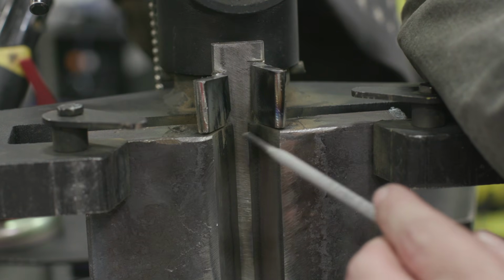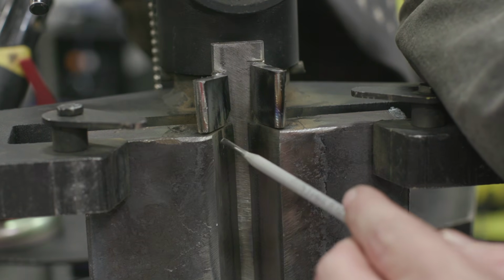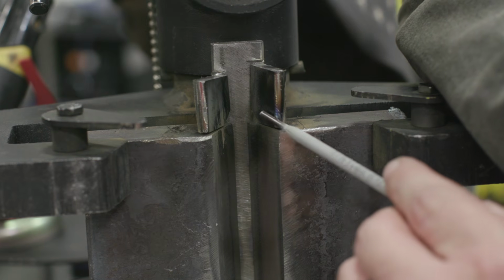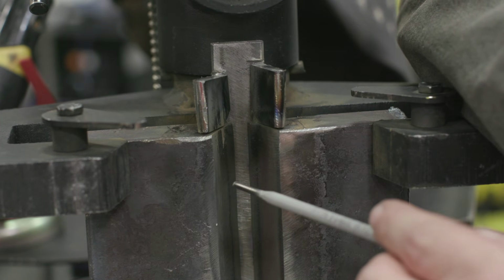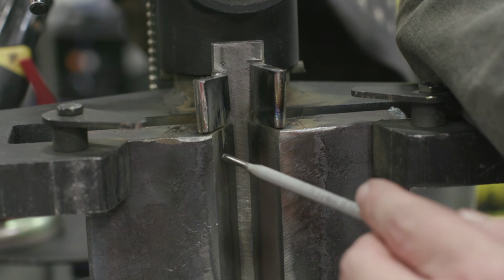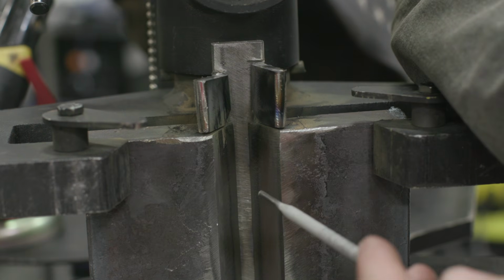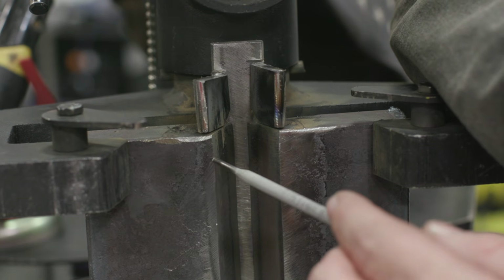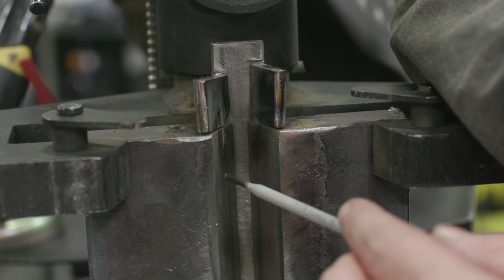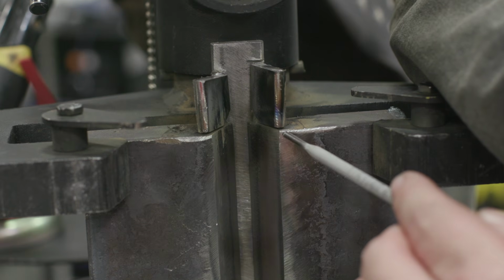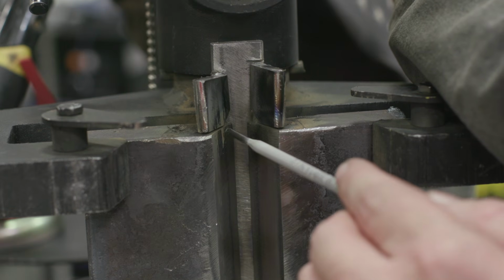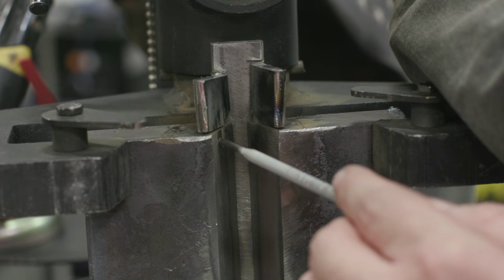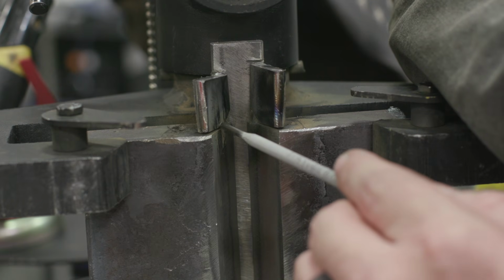So once I get to my cap, I'm not low at the end here, because everything has to be flush to 3/16 on a 1-inch plate. I'm allowed to go up to a 3/16 weld reinforcement, whereas with a 3/8 plate we're allowed 1/8 inch. With the 1-inch plate I can have up to 3/16. So I want to make sure I have proper fill, so I don't want these corners or these edges here to dip in. I want to make sure I'll be able to fill those up.